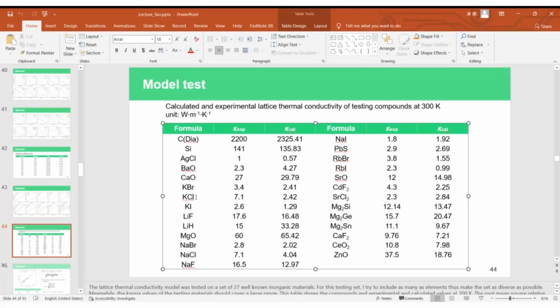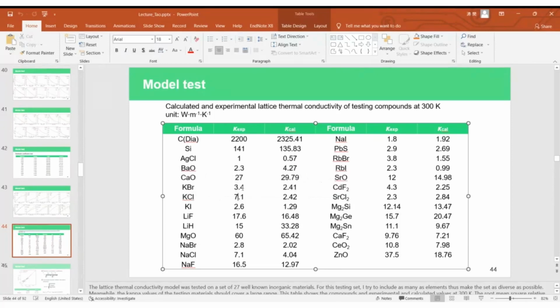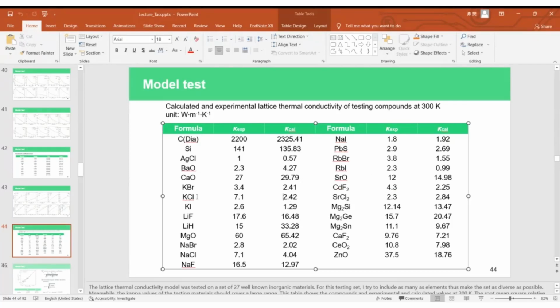So even, for example, we know this compound is a very stable compound, I mean its experimentally measured lattice conductivity—no, experimentally measured Grüneisen parameter—is perhaps just 1 point, etc. But I found my calculated Grüneisen parameter is a bit large, maybe larger by 0.5 or 0.7. So even such a small difference will make the final results quite different, quite a lot. So I think the difference is mainly because our calculated Grüneisen parameter is not very accurate, it's overestimated, so the calculated kappa is underestimated.